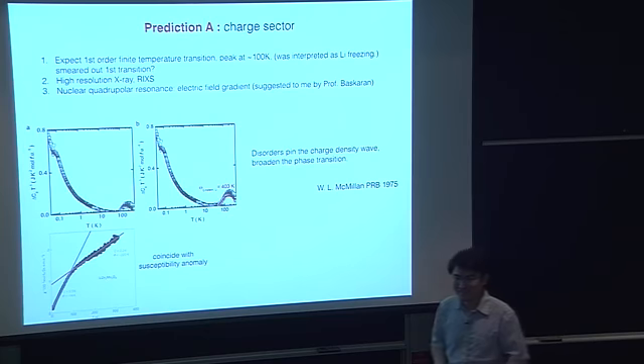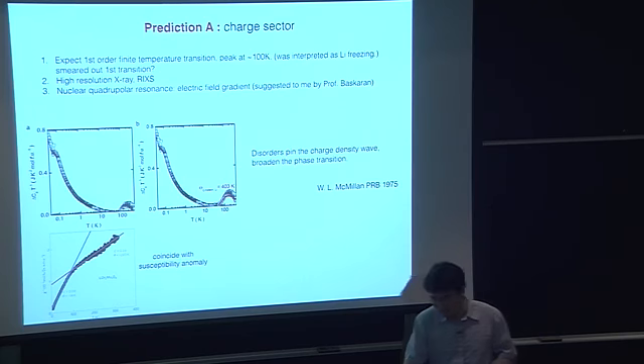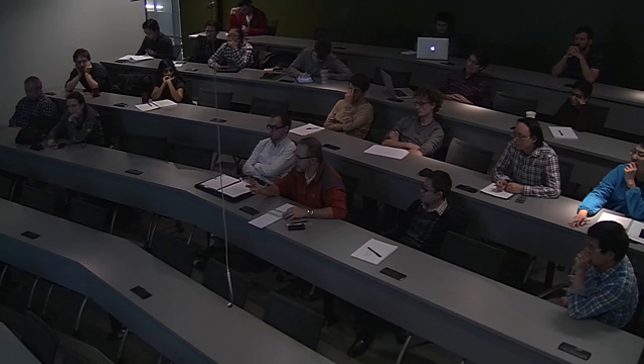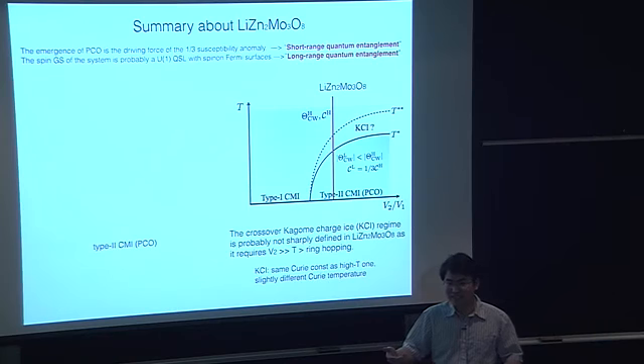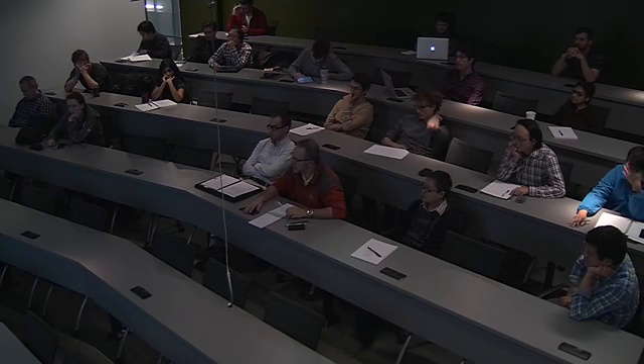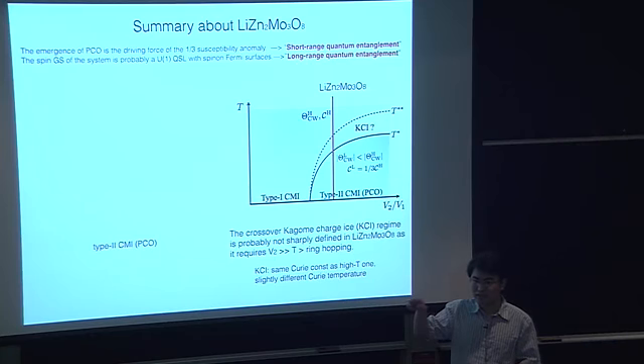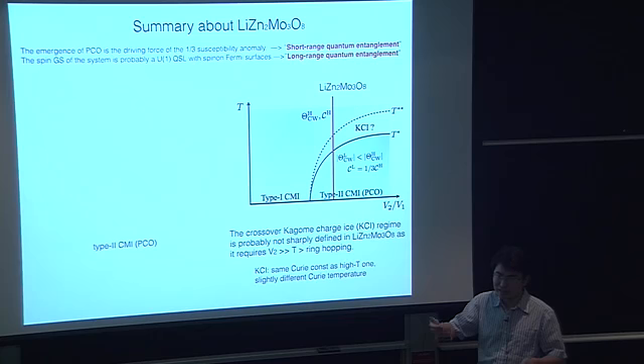It's not clear? Yeah, I understand that. But what's the order parameter symmetry? The order parameter is the charge density wave. This plaquette charge order is three symmetry-equivalent discrete states, right? So it's just electron density. So what's the order parameter? Is that a three-state Potts type order parameter? Yeah, it's like that, but there is a cubic term in the theory because of the tripling of the unit cell. Usually, in the coarse-grained description, I write the density in terms of phi times e to the i q times r. Is it clear? No? Yeah, maybe we can talk after.